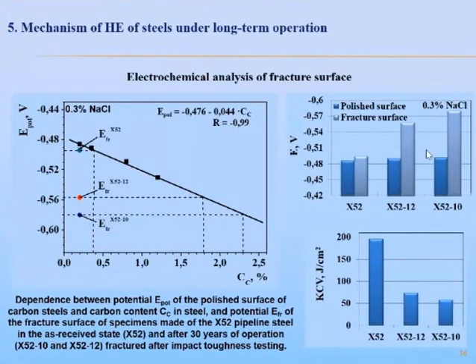Such a significant difference in the potentials can be explained by the fact that the fracture surface is the result of propagation through local sites characterized by minimal resistance of the material to fracture. Therefore, changes in the metal that were initiated during long-term operation and caused its mechanical properties degradation are the most distinguishable on the specimen fracture surface.